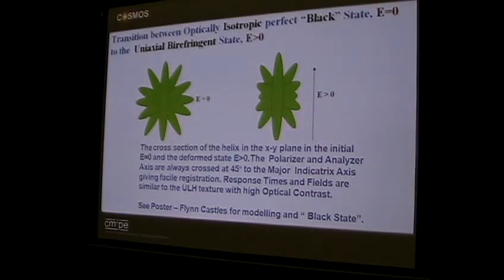From above is where you get the difference. Because if I have no field applied across my system and a short helix pitch, a pitch shorter than the wavelength of light, and looking down on the system, it looks optically isotropic. Because you have as many molecules pointing in every direction, or an equal number pointing in every direction. So it does look like water if you put it between crossed polarizers. It is optically isotropic. And that gives you a black state. Apply the field in the planar device and the optic axis tilts, and it becomes uniaxial. So providing you align your polarizer and analyzer 45 degrees to the field direction, you have a very useful display device. The black state is black. The light state can be made perfectly transmitting. And you can switch it in 20 microseconds. So it leads you to a high contrast, very fast flexo-electric device.